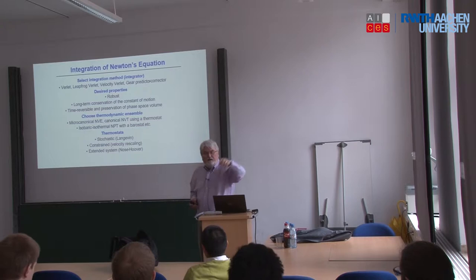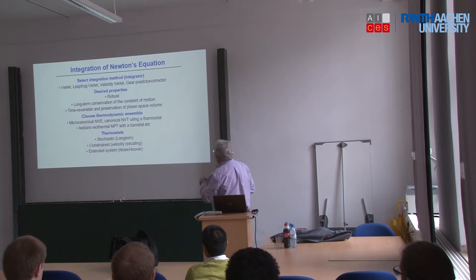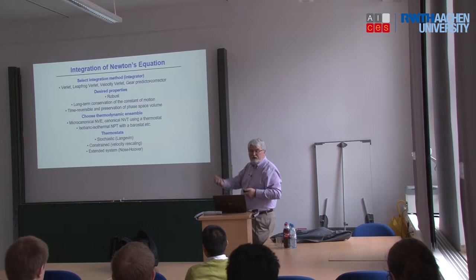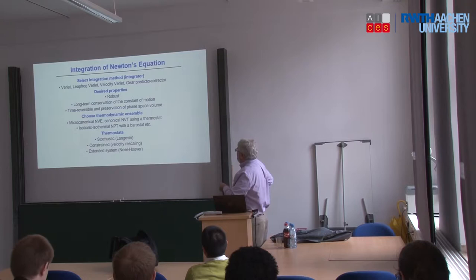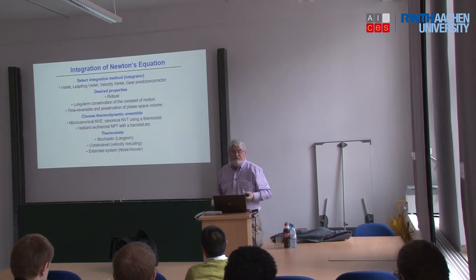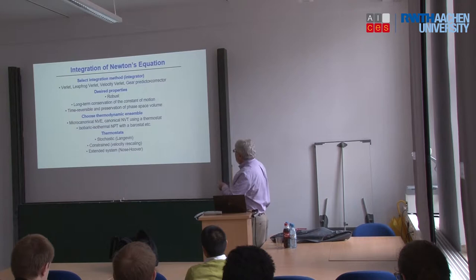And so what you want from these methods, you want them to be robust. That means you don't want it to break. You don't want to put a simulation on and then it fails for some reason. The math goes crazy and you get infinities. That's not good. You want long-term conservation of the constants of motion. So that says you want to conserve energy and momentum, for example. And there's other more. You want time reversible. You want to preserve phase-space volume. These are other requirements from a mathematical point of view.